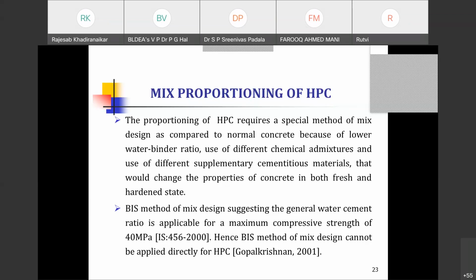Then mineral admixtures, you have a large number of varieties, from fly ash to silica fume. They are available, but what are your performance characteristics or the intended properties? Based on that, you have to go for choosing fly ash or silica fume or GGBS, like that. If you want more than 100 MPa, of course, you cannot depend on fly ash alone. You need to go for silica fume also. But if you are dealing with less than 80 MPa, there is no need to go for silica fume. With fly ash alone or GGBS, you can manage up to 100 MPa. So you need to think of what your requirements are, and accordingly, the mineral admixtures are to be chosen. You can go for combinations of these things also.